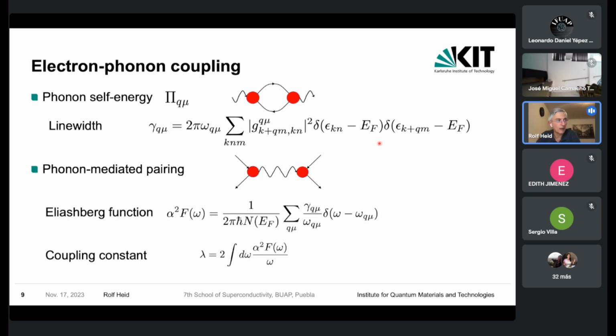The second quantity, which is now more relevant for the remainder of my talk, is the phonon-mediated pairing within the Eliashberg formalism, which has been very nicely outlined by the previous speaker. And as he also mentioned, the central quantity at the end we would like to have is the so-called Eliashberg function, and that can be expressed now in terms of these quantities I just introduced, but it's just a simple summation here, where these line widths enter relative to the phonon frequencies. And the spectral integral of this Eliashberg function gives then the so-called coupling constant, which is a dimensionless constant defining the strength of the coupling of the overall system with respect to the superconducting pairing.